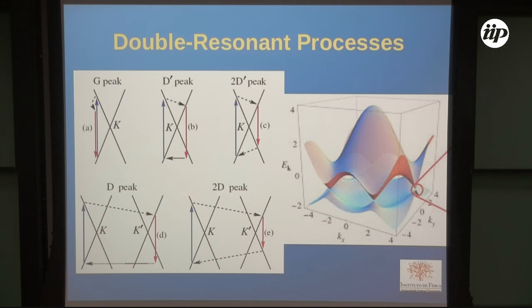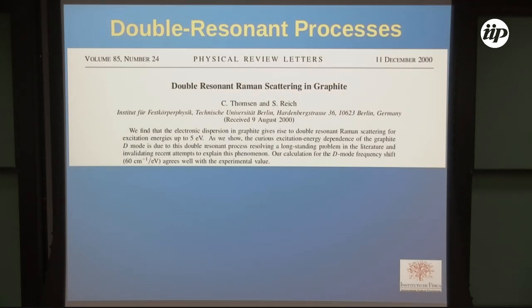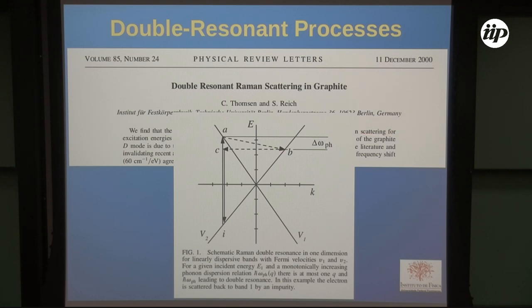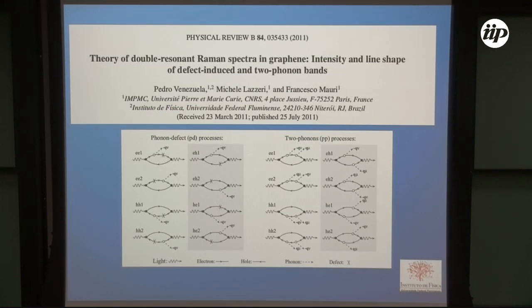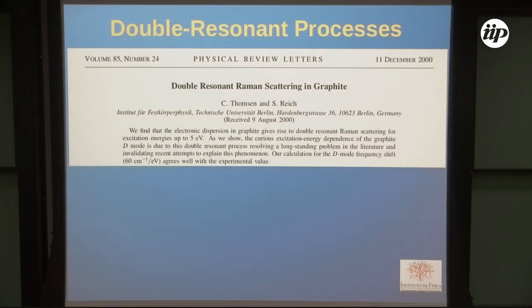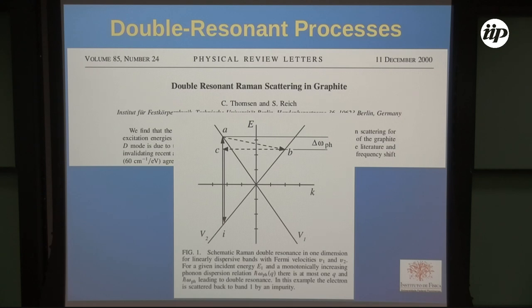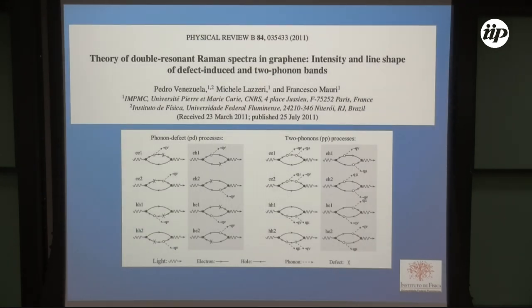There are also these peaks that are not so intense, but they appear where the scattering occurs inside the cone in the electronic structure. So that's the model that was actually proposed firstly in this very nice paper by Thomsen and Stephanie Reich, where they are the first to get the right mechanism and the first to see that the important thing to understand the D peak and the 2D peak is to pay attention to momentum conservation, okay? But it was in 2000, and even more than 10 years after this paper, they have some calculations here, but there was not a very, how can I say, accurate and detailed calculation about that.